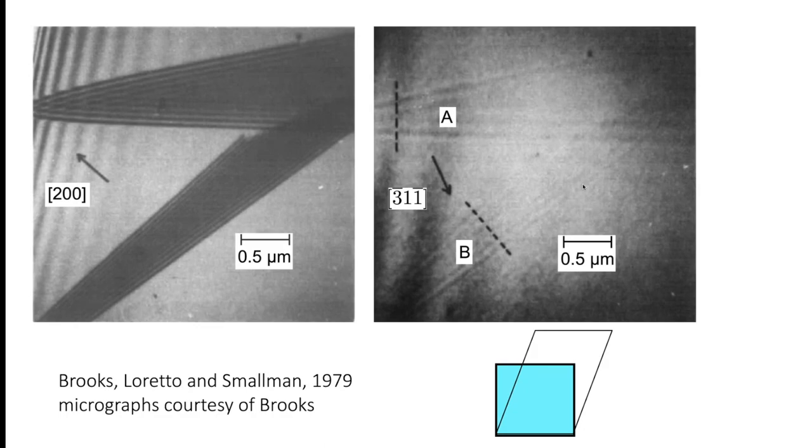And this is the first ever experiment to prove that the faults we see are actually thin regions of hexagonal close-packed martensite. What they also did was add alloying elements so that the lattice parameters change, and therefore the density difference changes, and they predicted that the residual contrast should change accordingly. And of course, it worked perfectly. So it's a very, very clever experiment to prove that you don't just have a shear deformation, right?